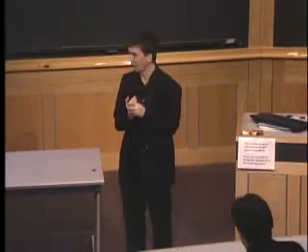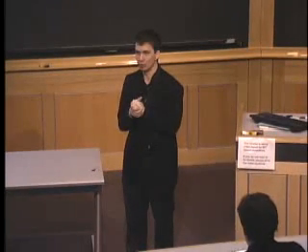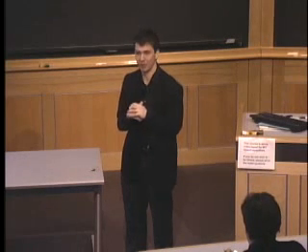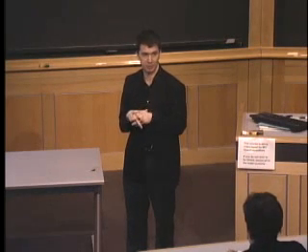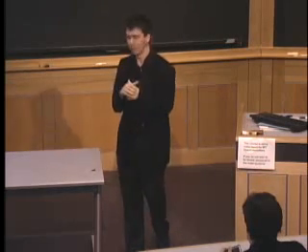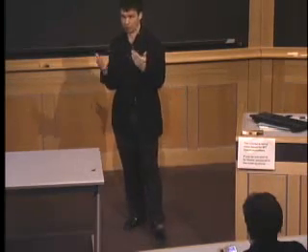And what you see is that actually the state with 2 atoms on top of each other is a highly bonded state in this kind of potential. So you will never escape it. You will really just put atoms on top of each other. And trust me, if you work with Born-Mayer potentials and you're not careful, you will see that. You will see atoms sit on top of each other exactly because of this problem.